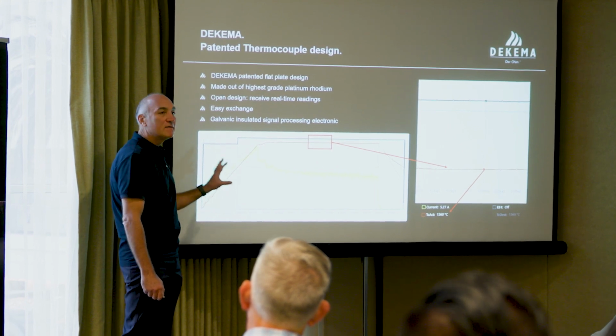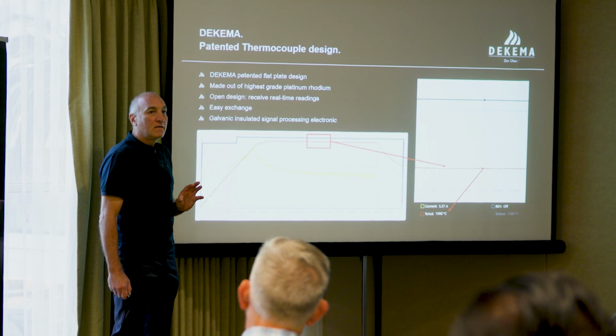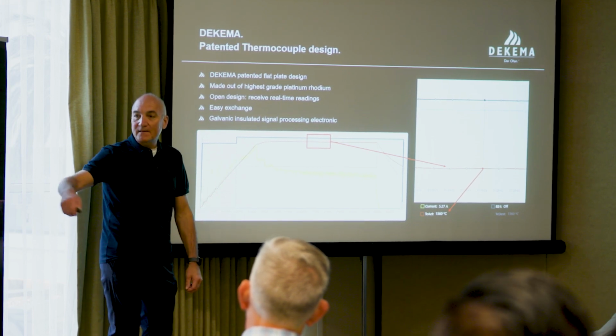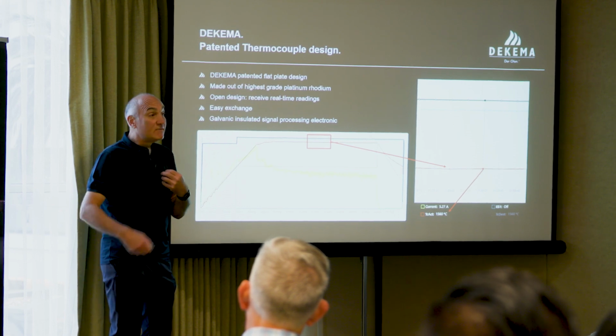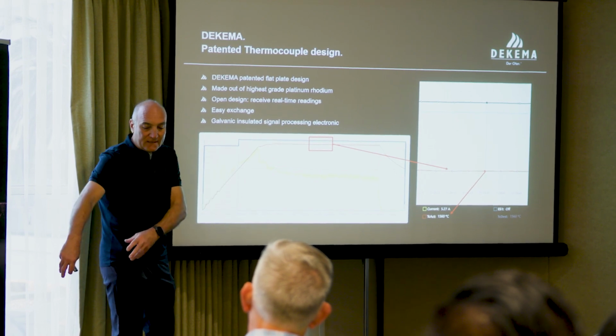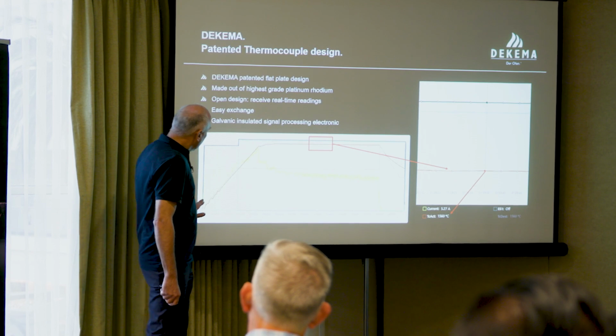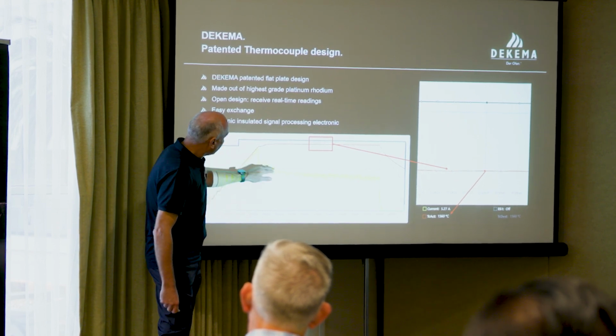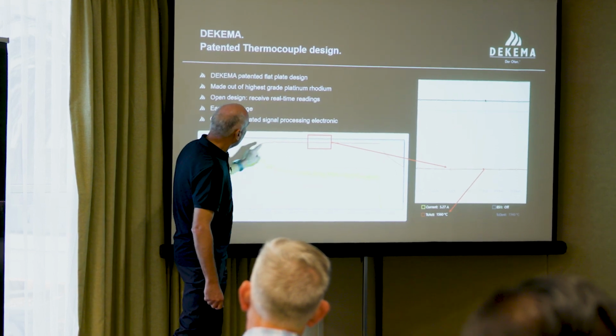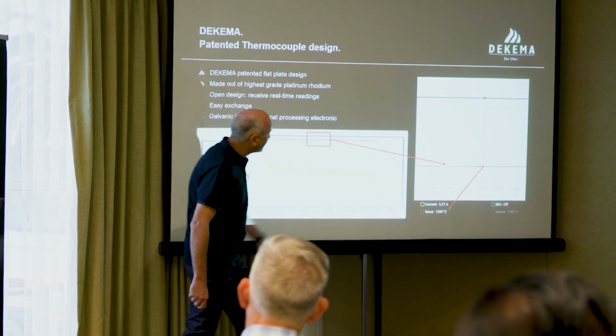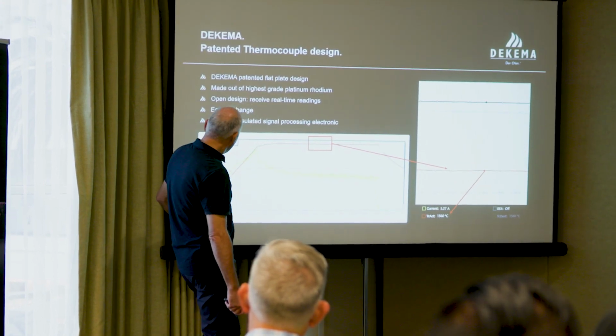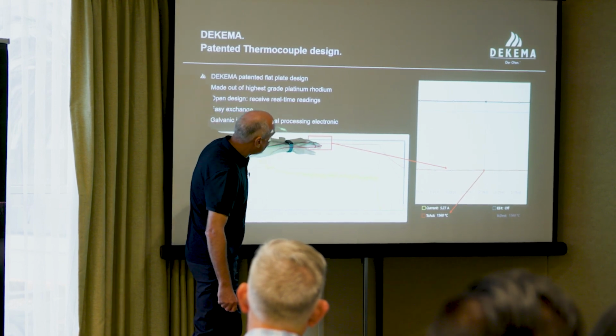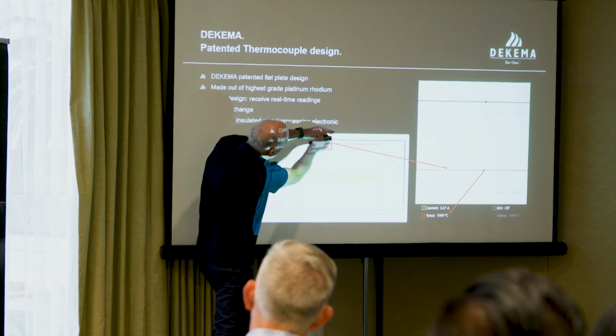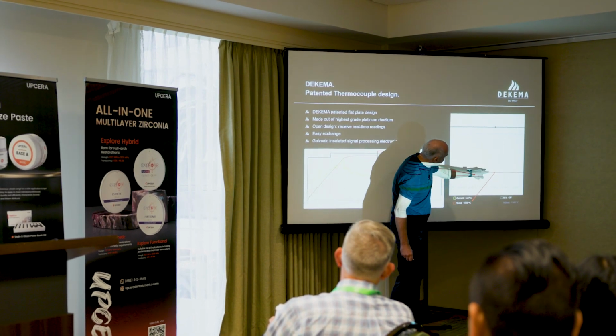Thermocouple. So as I said before, what you see here is one of the data of the information we get from every single cycle. With the Series 6 furnace, that's stored inside the furnace. With a backup, we get it into the database. With a Series I furnace, the furnace even sends us the data to have it already stored inside our database. In this case, you see the power consumption, the lift movement, and the temperature as it is and as it should be, actual and destination temperatures. And now we move up with the temperature to somewhere around 1500 degrees, or 1560 in this case, and you hardly see any deviation.